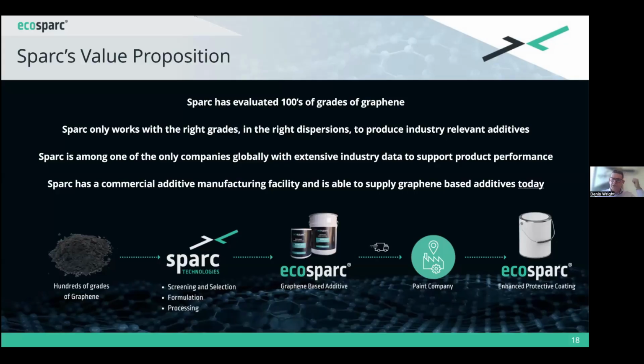So the value proposition, there's hundreds and hundreds of sources of graphene out there. They are all good for something. Some will be good for tires or tennis rackets or anti-static coatings. It depends on what you want to do. We've evaluated hundreds of grades of graphene. A very small percentage of those hundreds of grades works within protective coatings. We know the reasons why it works, and we understand that. Hence that we're now getting reliably good results of scribe creep corrosion, and also the other supporting tests that we do to demonstrate that.